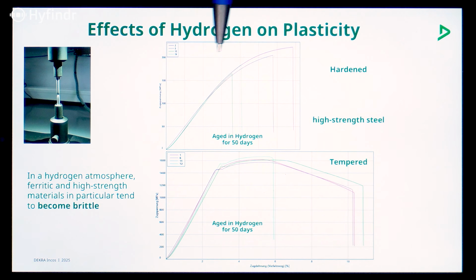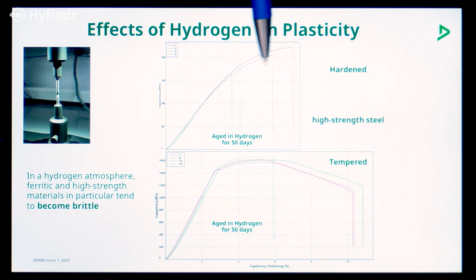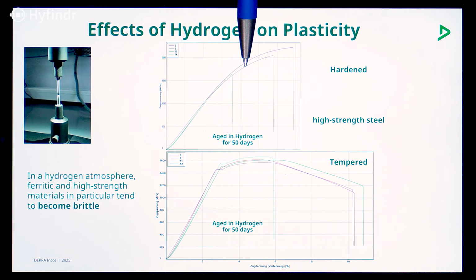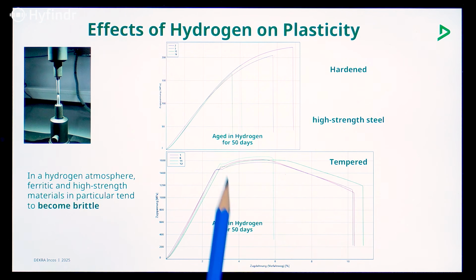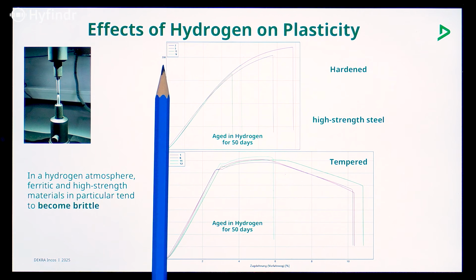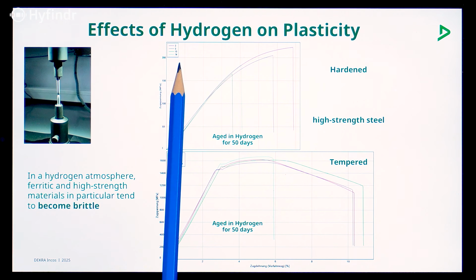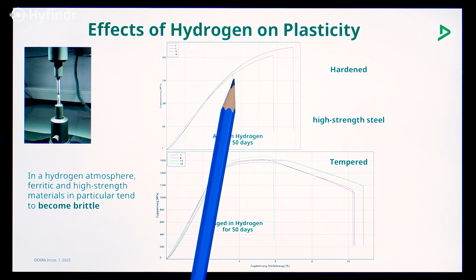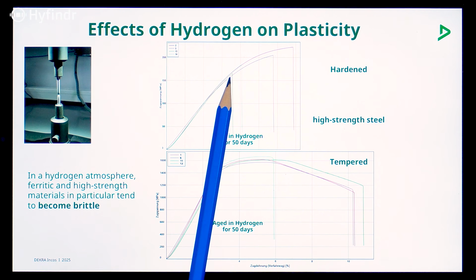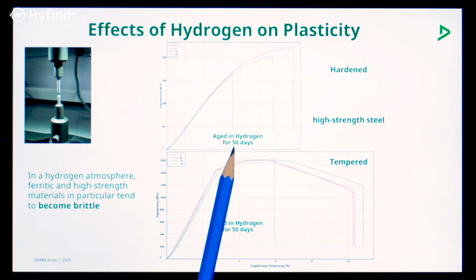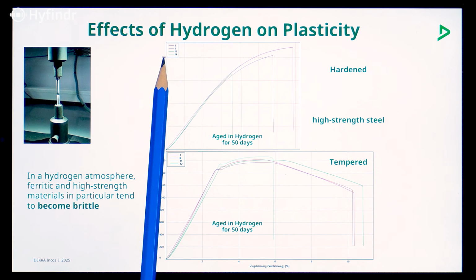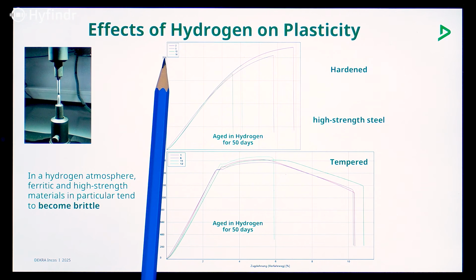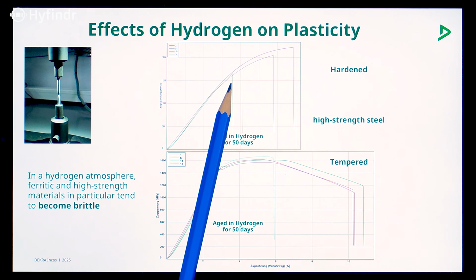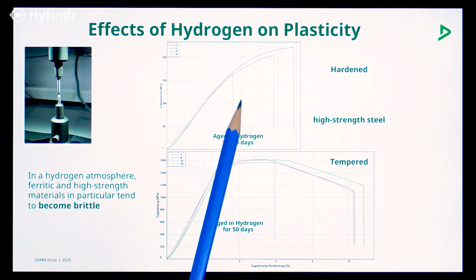So for hardened steel, there is also an effect. What is the effect here on the plasticity? It's the same. The x-axis is the same. Hardened steel has a very high strength. You see it here. It's a lot of strength. But if there is an aging process in hydrogen, we won't come to the high stress, because we have so much internal stress. So that the breakage comes very early.